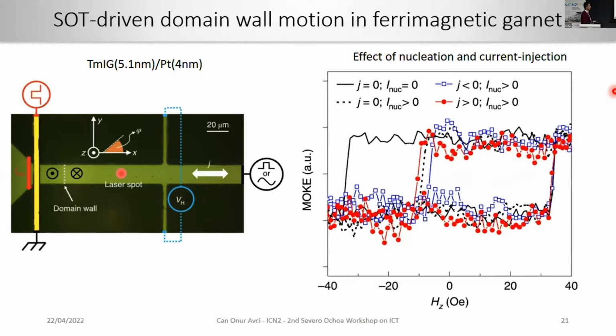So this experiment was basically to show you that once you have a magnet, this is the device we used, of course, and we use a laser spot to probe the magnetization at this point. And here we use a nucleation current to nucleate a domain and a domain wall. And by running a charge current along this wire, we can move this domain wall. So this is the hypothesis.